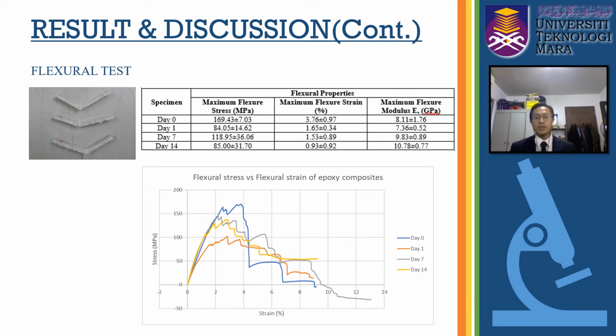The table shows the maximum flexural stress, maximum flexural strain, and maximum flexural modulus of the epoxy composite. We can see that the flexural stress and strain of the 0 days is higher due to the performance of the composite. The graph shows all the curves displaying identical patterns, which is when the load is increased, the material could not sustain it and eventually broke. We can see that the graph is linear in the first stage. It is because the stress of the composite increased when putting some load, and the graph slightly decreased when the composite cracked a bit.